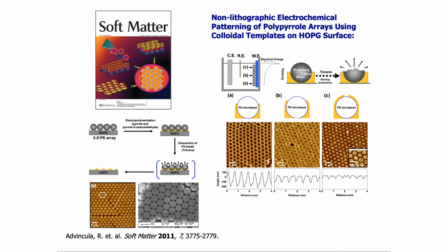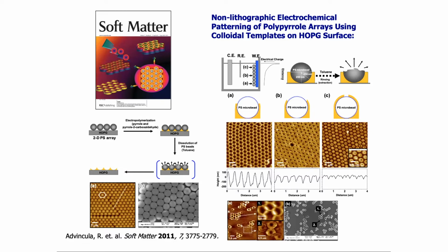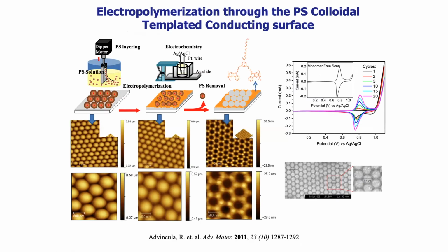So depending on the current or the voltage, you can have potentiostatic or galvanostatic control, or changing current. We can get a half dome, full dome structure. We can even remove these particles by delaminating it from the surface. So using this templating strategy, we were able to demonstrate that you can make conducting polymer arrays by varying the type of initiation and the monomer that was used.